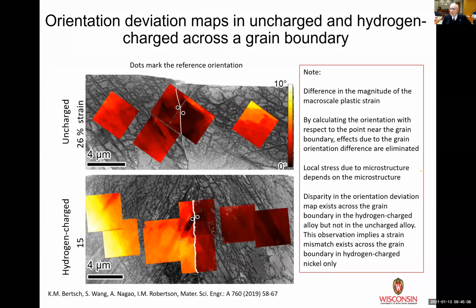So one of the things I told you can do is you can start to think about imaging the local strain. You can get information from the microstructure. I've shown you how to do that, and I'll take you back to that in a moment. But you can also visualize it. So I said earlier that you could do EBSD on an electron microscope specimen using the beam size of an electron microscope. So the one example you see here is, again, nickel. It's hydrogen charged, it's uncharged. The hydrogen charged is 15% strain. The uncharged is 26% strain.